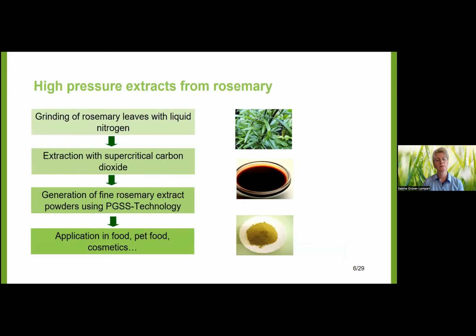To get a concentrate of these antioxidative ingredients, we do an extraction process with supercritical carbon dioxide. Before that, there is a grinding of the rosemary leaves with liquid nitrogen, because we have to avoid temperature and oxygen stress before the extraction, because then we would lose a lot of ingredients. Normally, the carbon dioxide extracts of rosemary are solid materials, which are not so easy to apply in many products. Therefore, we generate a fine extract powder using the PGSS technology. And this fine powder is easy to apply afterwards.